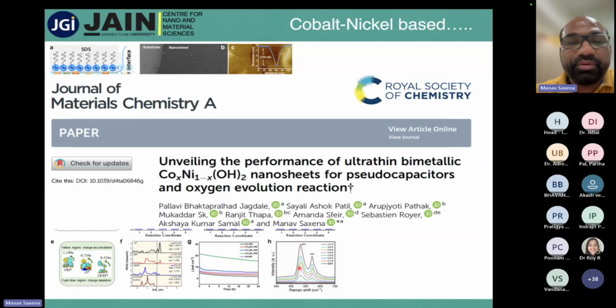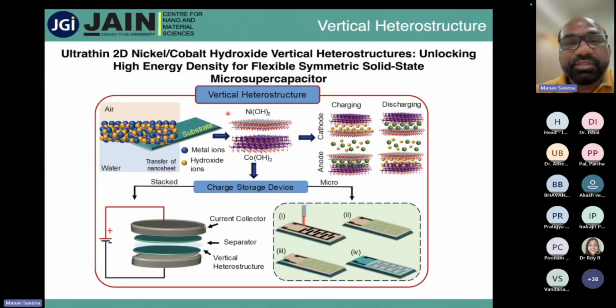So recently we have published this one, and now comes the vertical heterostructure or van der Waals heterostructures. As per my best knowledge, this is the first study of a transition metals vertical heterostructure of a large area. So what we have done, as I have shown in the previous slide, we made a cobalt hydroxide film. We transfer the nickel hydroxide film on that.